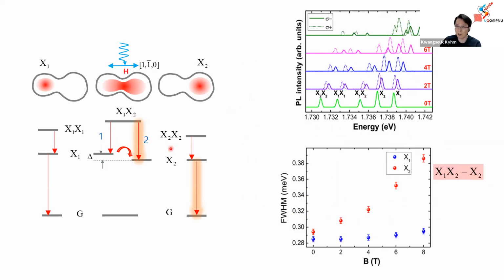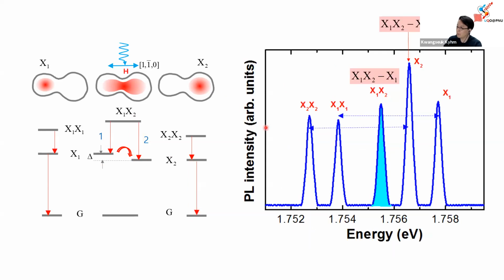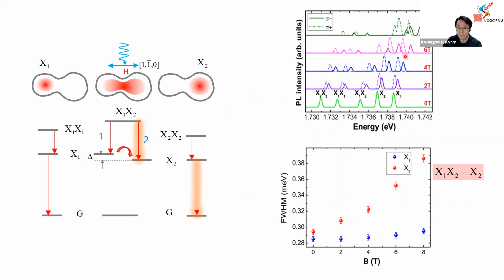Okay, to confirm our idea, we performed magneto-micro-photoluminescence. So our idea is very simple. If 2 spectra are overlapped here, one is from the coupled biexciton with a different wave function extent. Here, X2 has a small wave function extent, so the diamagnetic shift will be different. So we expect a separation. But 8 Tesla is not enough, and spectral resolution is limited. So it was difficult to separate these 2, but we checked the line width. X1 is small, but X2, which is overlapped with the transition 2, the line width increases fast. So 2 emissions are overlapped.